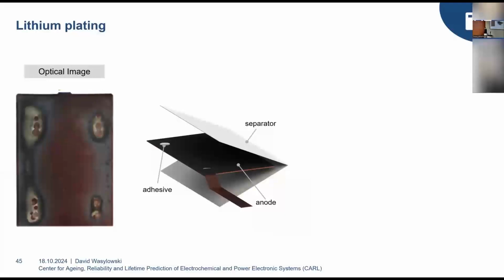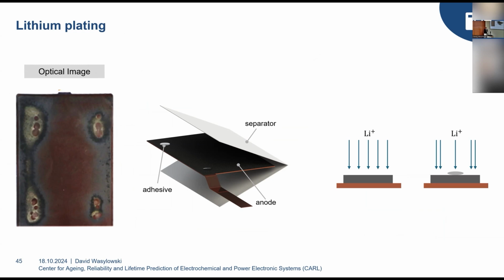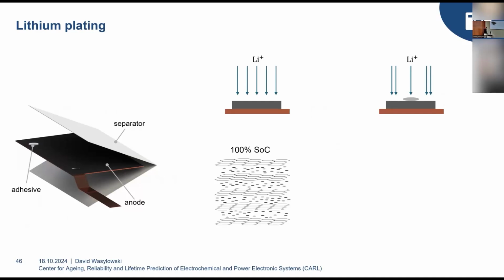So in order to understand what's really happening here, let's have another look at this anode. And next to it is this illustration of what we believe is happening during cell assembly. So we have this anode and these adhesive dots that are supposed to glue the anode to the separator. And now we need to understand what the difference is between an anode which is charged homogeneously and one which is charged inhomogeneously, for example, by this locally distributed adhesive that is impeding the lithium-ion flow between the cathode and the anode. And we already talked about the homogeneous case earlier. So this is this graphite structure, and those lithium ions are being placed inside this graphite structure. And when there is no more room left within this anode, we call this 100% state of charge.